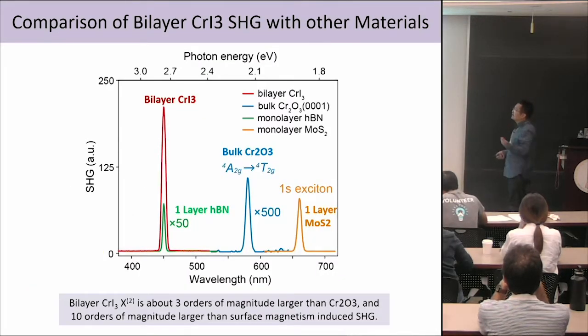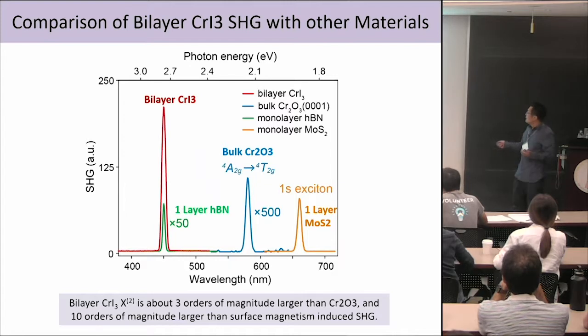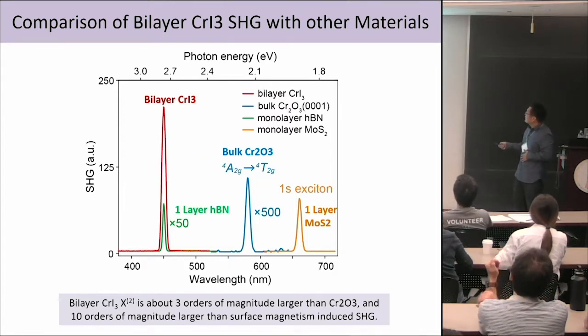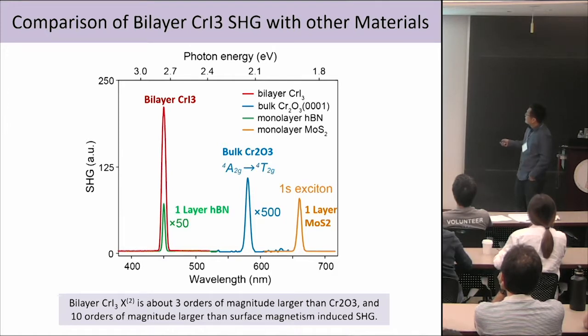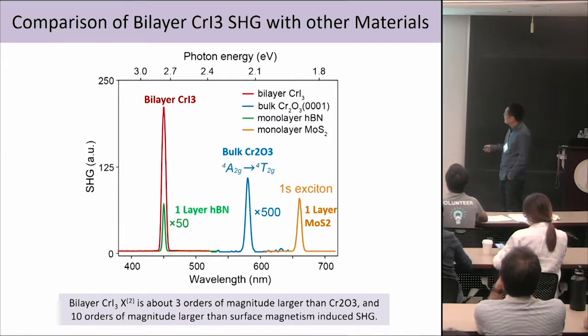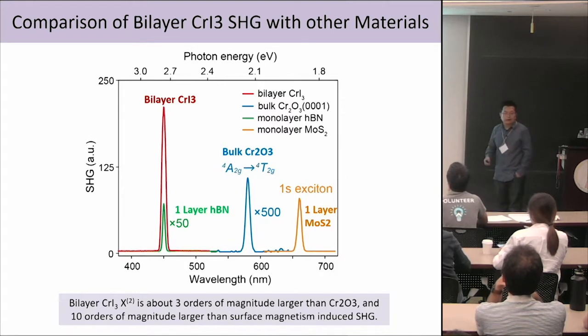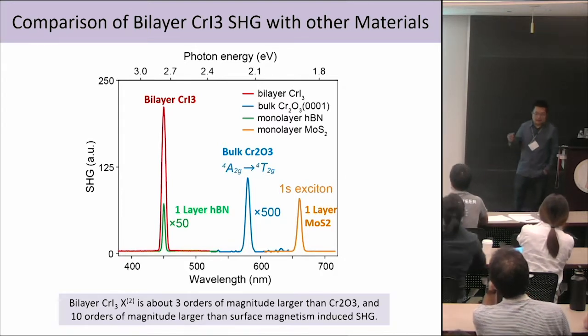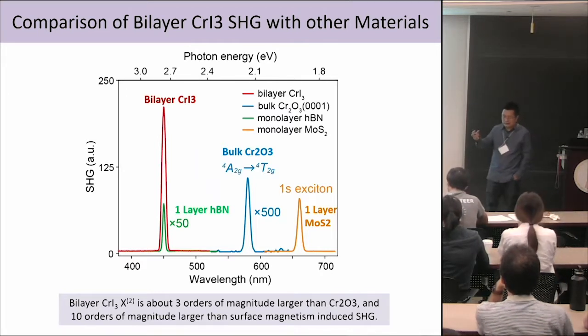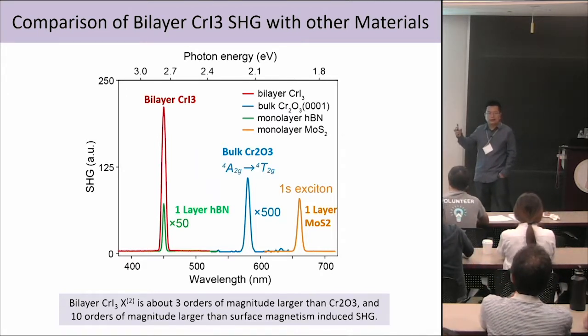And we can also quantify the strength of this second harmonic signal. It's remarkably large. So here I compare, for example, the second harmonic signal from the classic example of a bulk crystal, chromium(III) oxide, which is an antiferromagnet. And the signal from this bilayer actually is about 500 times larger than this bulk crystal. We can also compare the SHG from other 2D crystals, like monolayer MoS2 or monolayer hBN. The bilayer CrI3 is also stronger, okay? So this gives us a kind of unique opportunity, right? We can control the magnetic order to switch this very strong nonlinear optical signal.